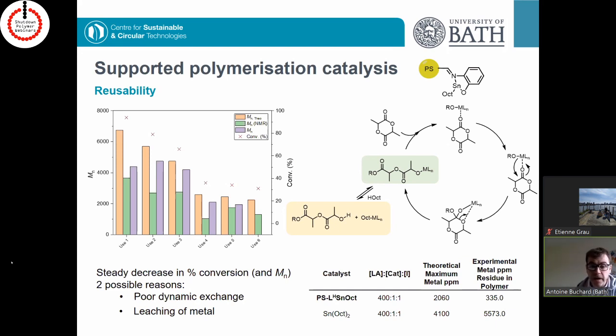Keeping an eye on the time here. And we've confirmed this by doing some ICP-MS analysis of the polymer we produce. And this is the data which is shown in this table, which is worth looking at. So this is the amount of ppm metals that you would expect if you had 100% leaching under this condition of our catalyst. And what you can see here is the experimental metal leaching is still there. Well, it's still limited, right, compared to something that would be completely homogeneous and without any washing, but there's still an amount of leaching that we can't deny.